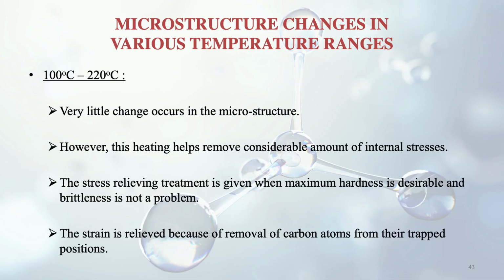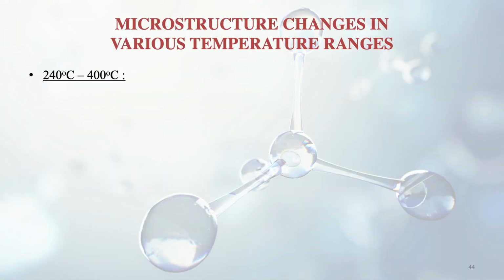In this case, the strain is relieved because of the removal of carbon atoms from their trapped positions. Earlier we have studied that in martensite, the carbon atom tries to occupy the position between the iron atoms, and that's what causes the distortion, and we get a body-centered tetragonal structure. We have discussed this earlier in the previous sessions. So this carbon atom now can be removed and we can get a better structure which will cause lesser internal stress. So after 100 to 220 degrees centigrade, now we discuss 240 to 400 degrees centigrade, what happens in this range.